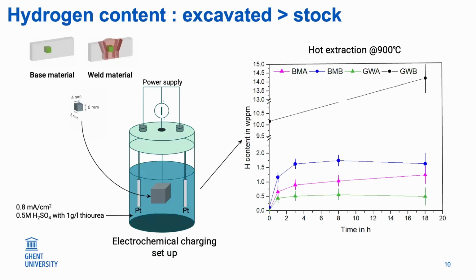Prior to all the mechanical tests that were done, it was necessary to know the condition that exactly saturates our base materials before the testing. So we extracted 6 millimeter cubes from the pipeline middle region and then electrochemically charged them at the given current density for different charging durations, and then hot extracted them at 900 degrees Celsius to know how much hydrogen we are actually putting into these samples. And we see that for all the charging durations, the excavated material shows a significantly higher hydrogen uptake at all the conditions.